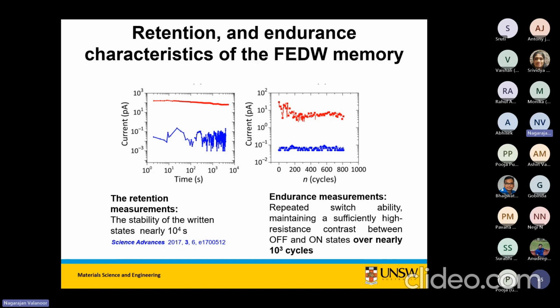We also did endurance measurements. Of course, if you look at the standard fatigue data in a ferroelectric memory or in any other memory, they want to go to a million cycles. Here again, the tip can only go up to about 800 or 1,000. That's enough for us. Basically, it showed very well that our idea of this domain wall memory worked very nicely in this model system. So then we went to the next problem.